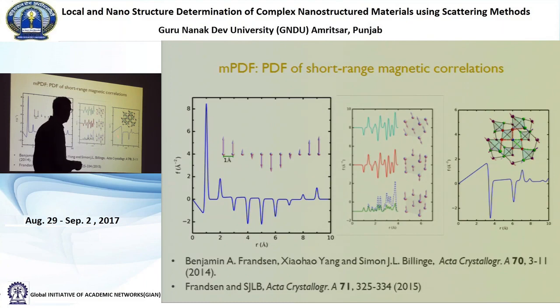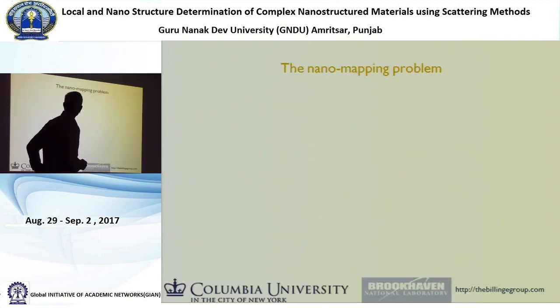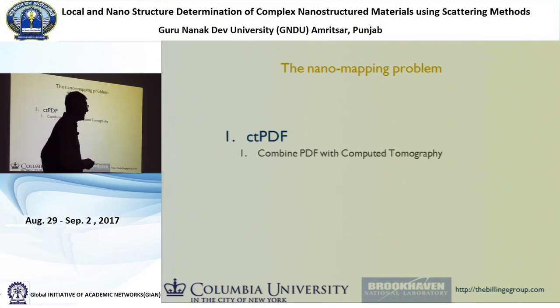So that's frustrated magnetism. And the pyrochlore lattice doesn't have triangles, it has tetrahedra. But the same thing happens with tetrahedra, and then it actually follows spin ice rules. So the Pauling ice rules are actually obeyed in this spin ice. But we can actually compute what the correlations are from a model of this. So this is actually a very beautiful thing. And I don't have examples in this talk, I'll show you maybe some later, but we can actually measure this very beautifully from data. And what you can see is short-range magnetic correlations, even when there's no long-range order. And so I think this might be the last example in this part of the talk, I'm not sure.